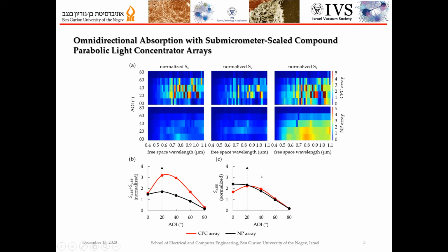Figures B and C show the broadband values of the lateral components, which are Sx and Sy, and the vertical component Sz, respectively. Evidently, the lateral components of the CPC array are considerably higher, with values 2 times greater than the nanowire arrays for AOI, angle of incidence, 40 degrees and 60 degrees, and more than 80% higher for AOI 20 degrees and 80 degrees, which is indicative of the ability of the CPC array to effectively bend the light under broadband and omnidirectional illumination. On the other hand, the vertical components Sz of the arrays are very similar, except for the normal incidence, in which the nanopillar prevails.